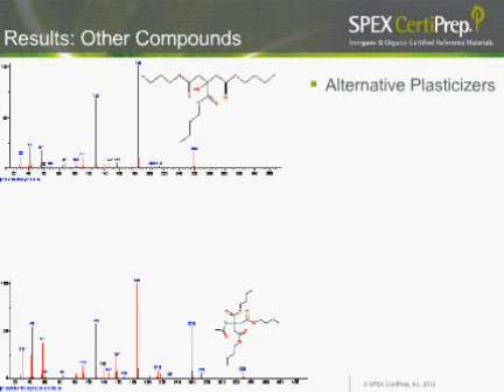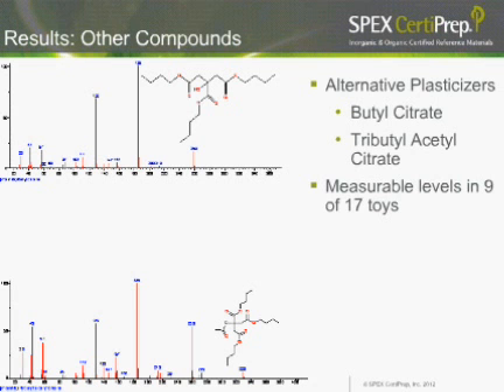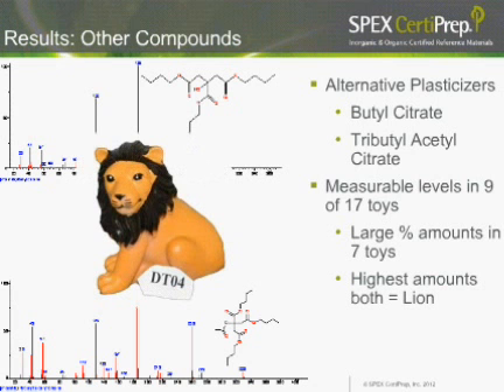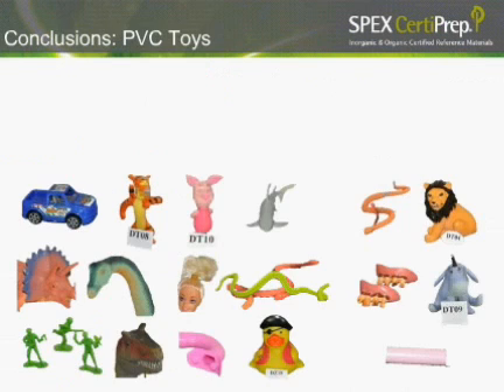One of the interesting things we found in our scan mode was alternate plasticizers, specifically a butyl citrate and tributyl acetylcitrate. We found this in 9 of the 17 PVC toys. And in 7 of those toys, the amounts were large enough to be in percentage quantities. The highest we found of these two particular alternate plasticizers was in our lion toy. And it was also very interesting, the lion toy had no phthalates, but it did have high percentage amounts of the butyl citrate and the tributyl acetylcitrate.